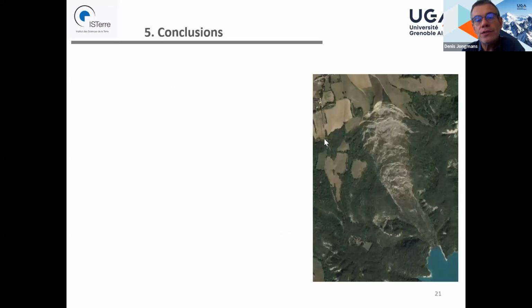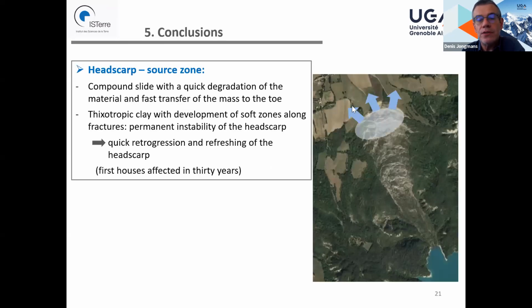So my conclusions are the following: at the escarp, so in the source zones, we have a compound slide with a quick degradation of the material and a fast transfer of the mass to the toe, so making free the space in front of the escarp. The clay is thixotropic at the escarp with development of soft zones along fractures, and so it contributes to the permanent instability of the escarp.